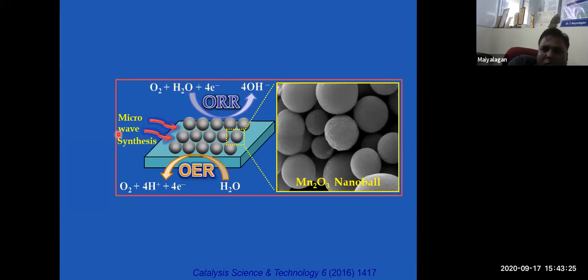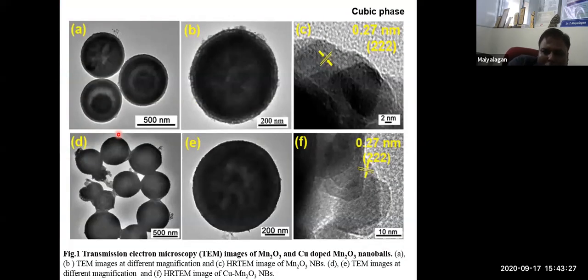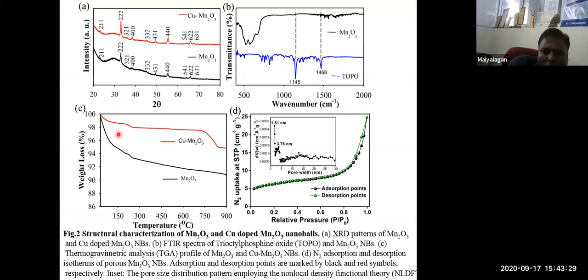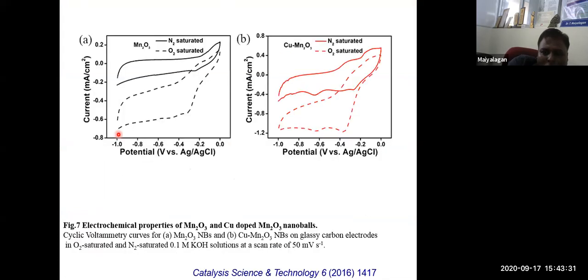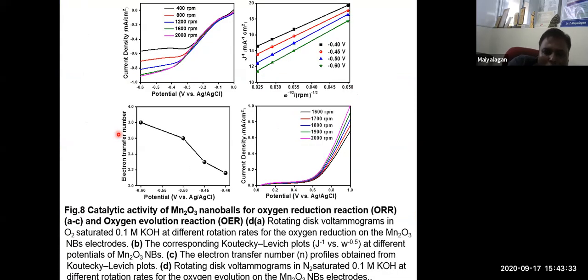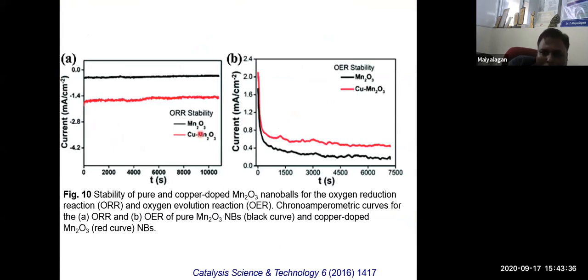So we tested some materials, Mn2O3 nanoballs and copper doped in Mn2O3. And we are getting good performance for Mn2O3 also. So this is the overall stability and oxygen evolution stability. As I said, for air battery performance, you need both reactions. The catalyst needs to perform both the oxygen reduction reaction as well as the oxygen evolution reaction.